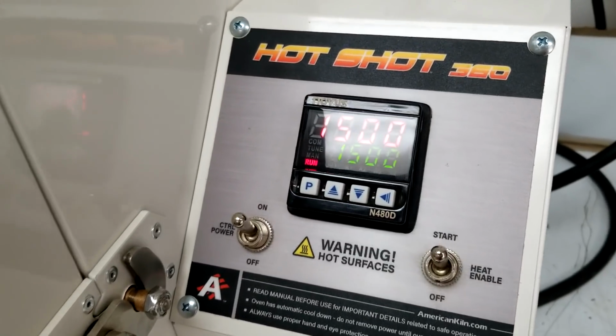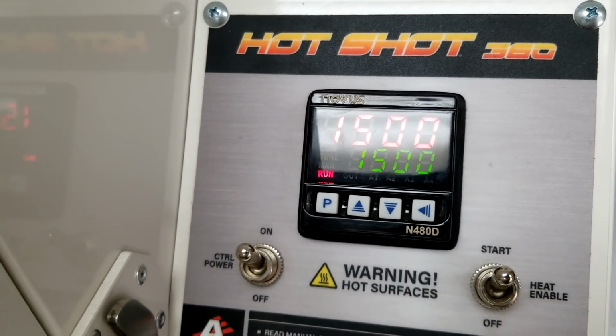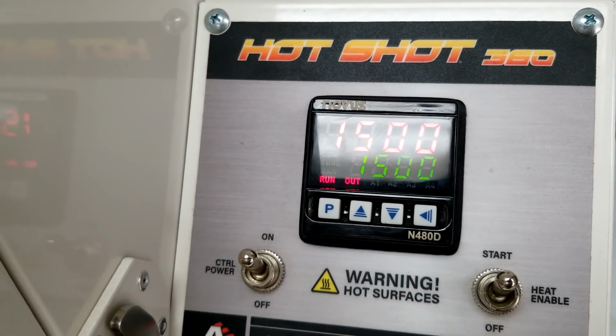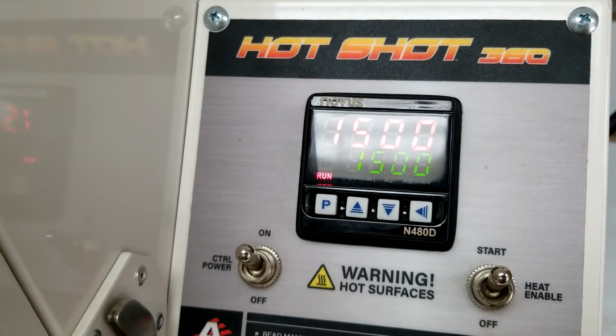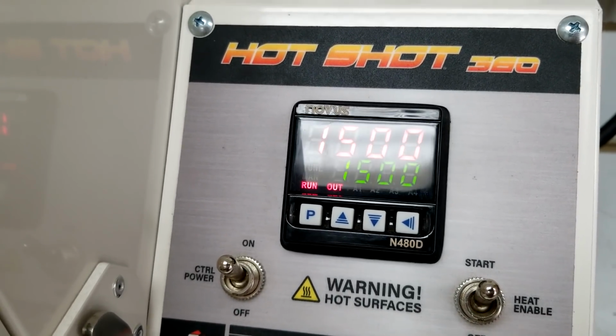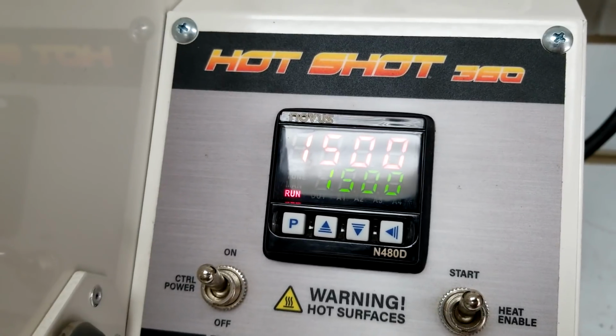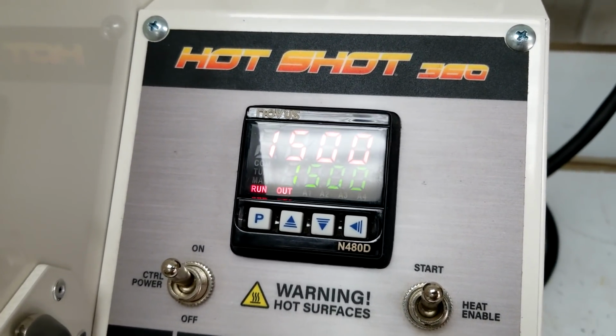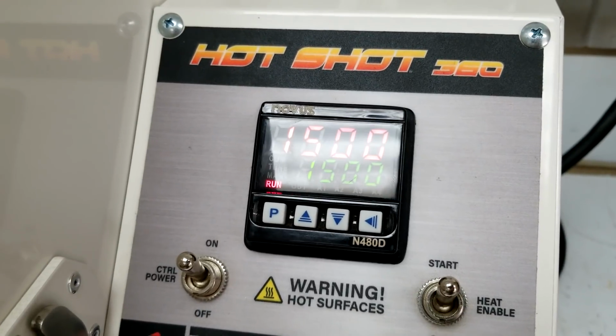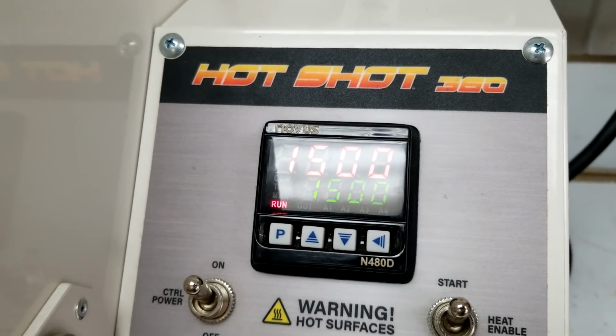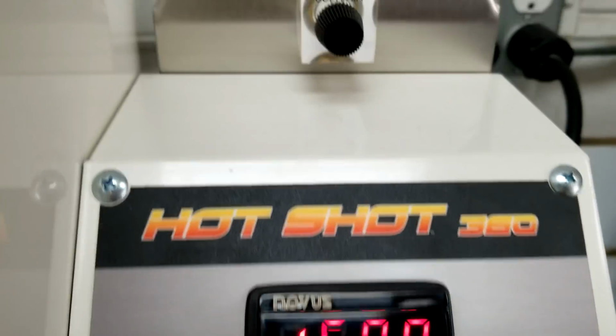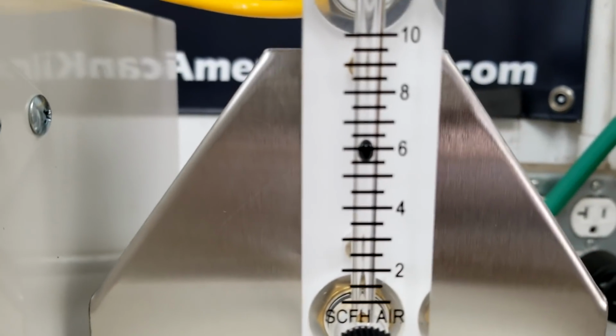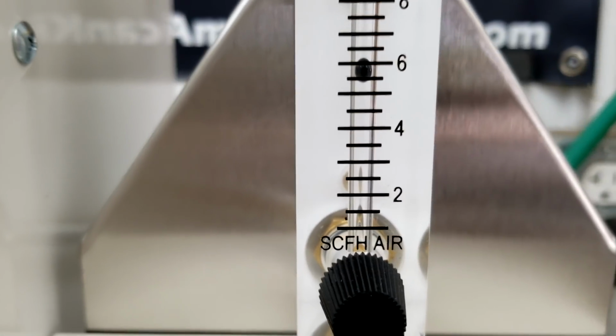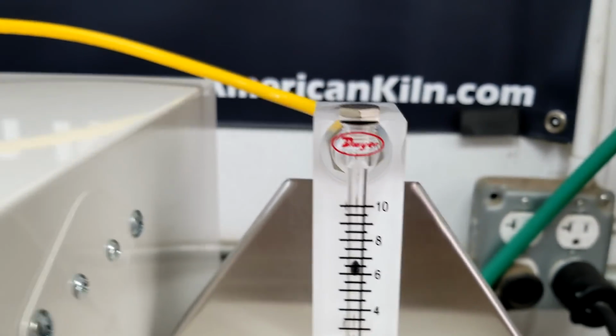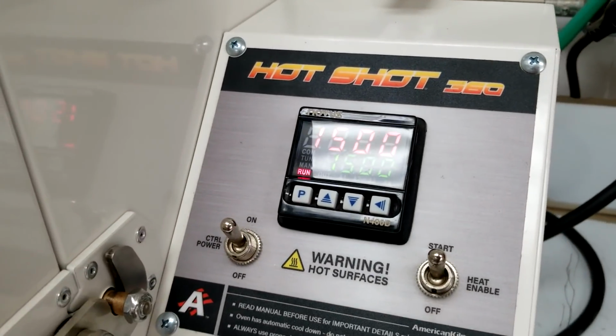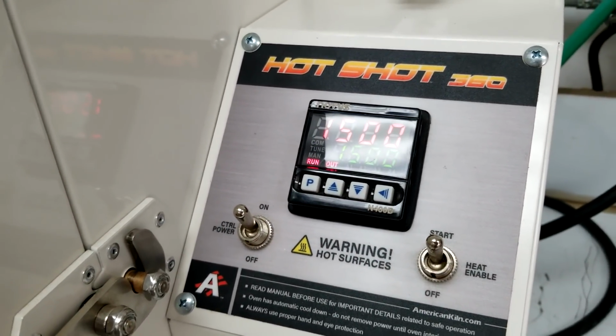Okay, well, we just arrived at our target temperature, which is 1500. It's now going to maintain that, and you can see our output light is just kind of chugging along there and tickling that element, just keeping it at temperature. So we're at a very steady 1500 degrees, and we're going to pull these parts in a half an hour. Just as I walked up, it went from 1499 to 1500. So we just hit target, and we're still flowing 6 CFH of argon into the oven, and when the alarm goes off, we'll pull our parts, quench them, and see what they look like.